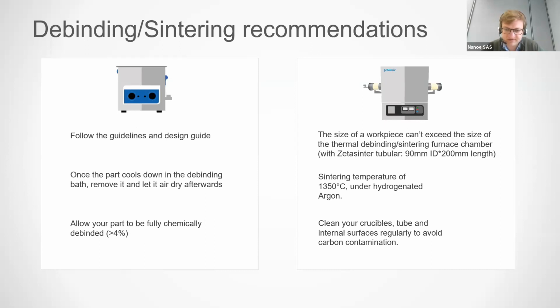Sintering temperature is 1350 degrees Celsius, and it's important to keep a clean tube and set a plate or crucibles depending on how you put your parts to avoid carbon contamination. That's really the crucial thing. 316L is extremely sensitive to carbon contamination. If you have too much carbon in your material, you don't have a stainless steel anymore. And that will also affect sintering temperatures, deformation, and all that. So this carbon contamination is really something we need to avoid at all costs, and to avoid that, the setter and the tube really need to be clean.